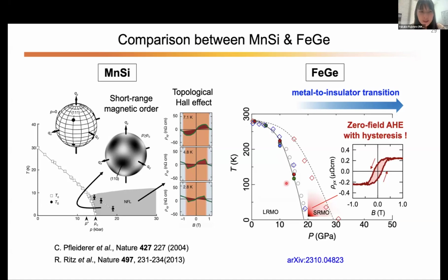Yeah, thank you very much for the great comment. So actually, I tried the scaling relationship, but it does not follow any of the conventional scaling mechanisms, even for the intrinsic mechanism and also the skew scattering, where the Hall conductivity is proportional to sigma xx. So I would say that this anomalous Hall effect is not conventional at all, and we need some new theoretical interpretation to understand this phenomenon.